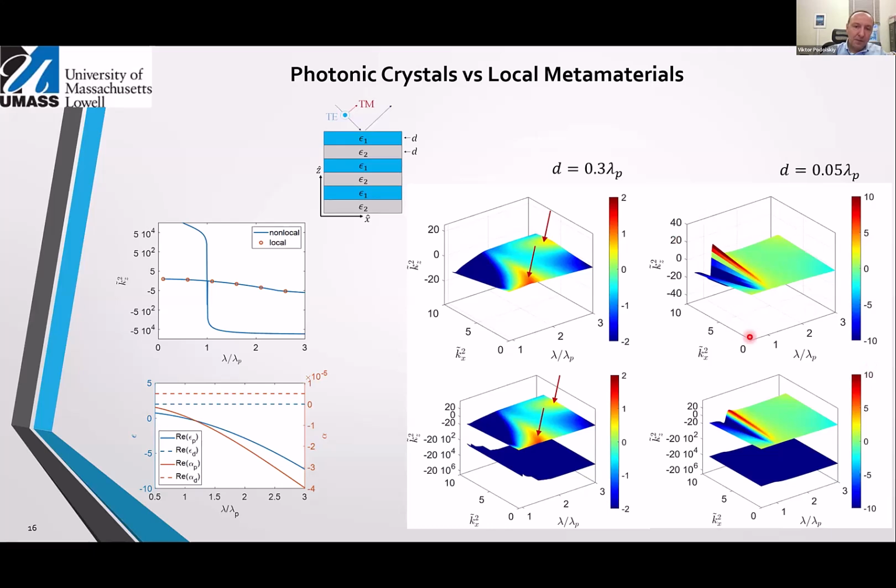That's your metamaterial. This metal-dielectric composite should exhibit, again, this hyperbolic transition. So that's the frequency of the elliptic to hyperbolic transition that you see here. This is just local calculations. And at the bottom, we see what would happen if you add non-locality. And you can see nothing happens other than, again, a second mode that evanescently decays inside the composite.